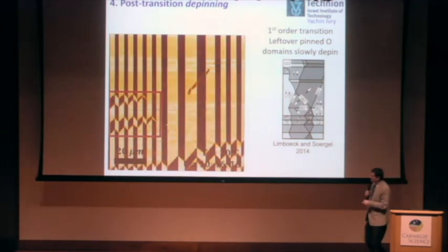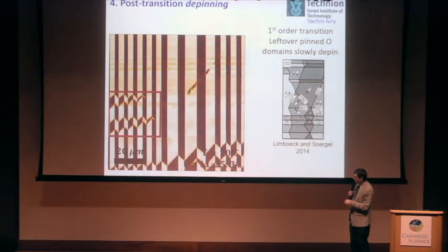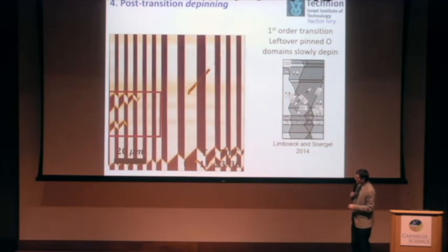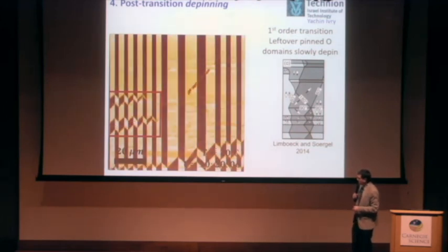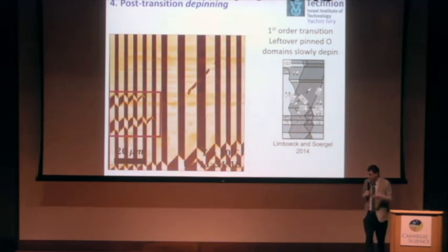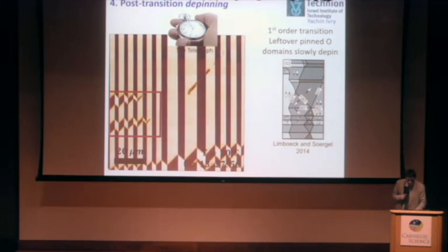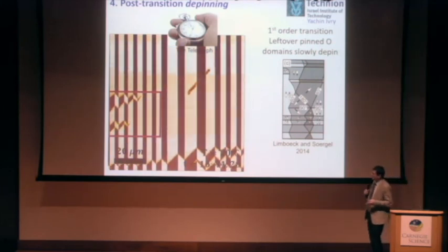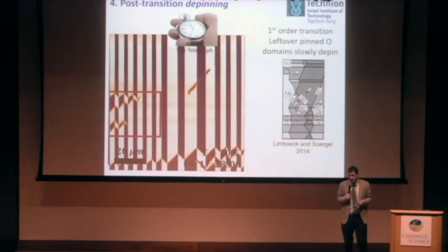So this is, of course, much faster than it was before. And you can see that the rate changes with time. But anyway, you see some kind of relaxation. The top one is going slower. This one is going faster. And then we stopped our experiment after about 20 hours, after cooling and heating the temperature by only a few degrees.